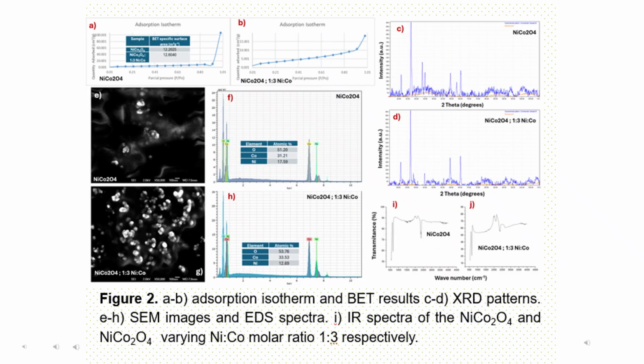On the other hand, the results of the nanoparticles BET analysis show a similar surface area. However, the sample that is rich in cobalt allows the development of a higher surface area structure. This property is favorable for catalytic applications.